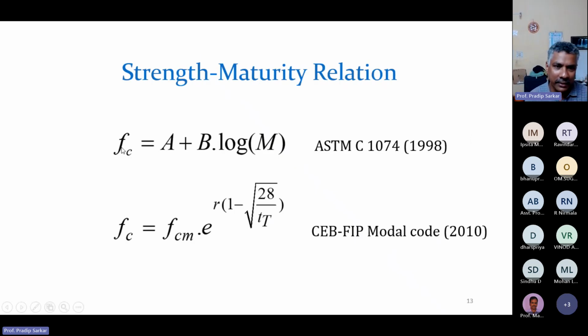So I have given here two relationships. One is proposed in the ASTM code, that is C1074, and later in the CEB-FIP, the European model code, where you can see the compressive strength is a function of maturity. It is logarithmically related. M represents the maturity, and here it is an exponential. There is a TT instead of M. This is also the temperature-time factor, and with an R and fcm, these are two other constants. Here A and B are two constants. Similarly here R and fcm are two constants. Otherwise it looks the same: a function of M and a function of TT. M and TT are somewhat similar.